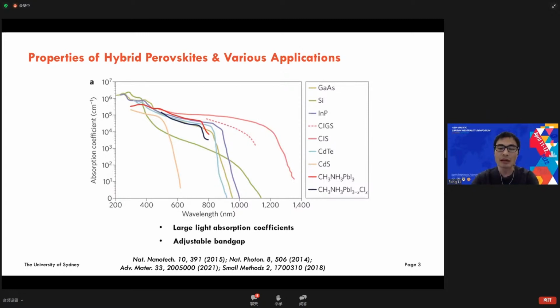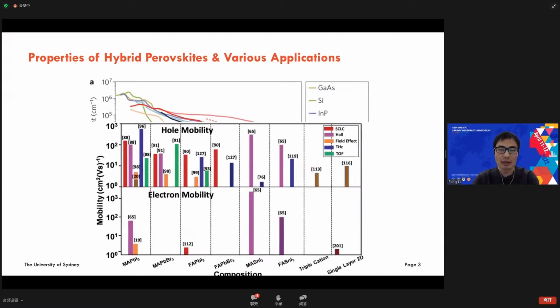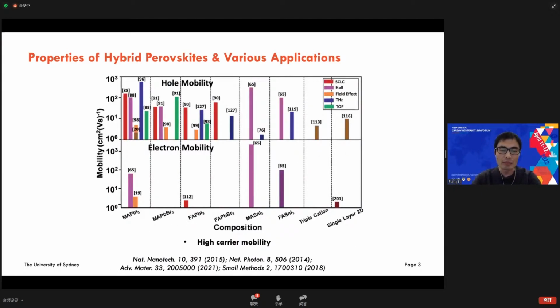and it's quite easy to tune the band gap of this kind of material by tuning the concentration of the elements, and also quite easy to change the form and the dimension of this kind of material. This material also has very excellent charge transfer properties. Based on different techniques, the mobility is more than 100, and it depends on the technique. So in the future, there will be more research on this point, in addition to the optical properties, also focusing on the charge transfer properties.